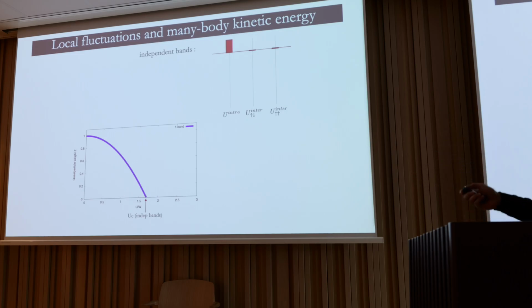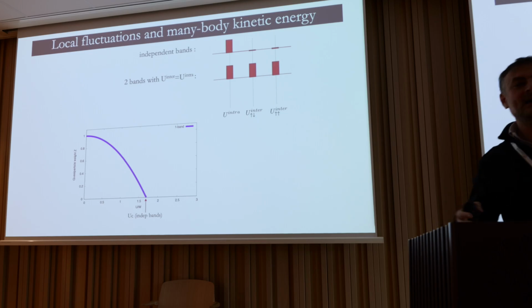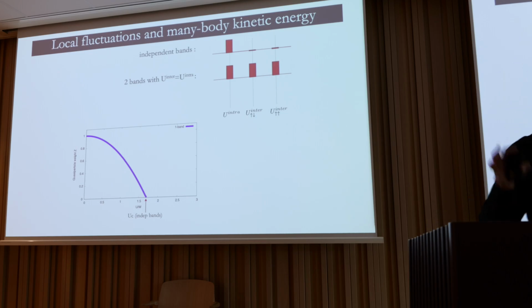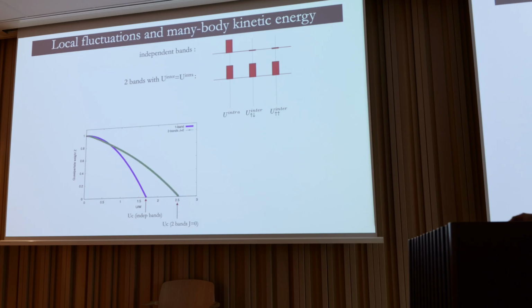Now this is what I have in this sum of single-band Hubbard models. If I turn on the repulsion between the orbitals, so I have more repulsion, you would expect increased correlations, and maybe a faster Mott transition as a function of the interaction strength. This is wrong—you get a Mott transition at larger interaction, which is somewhat counterintuitive.